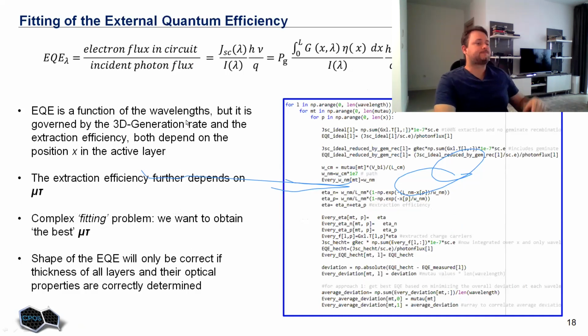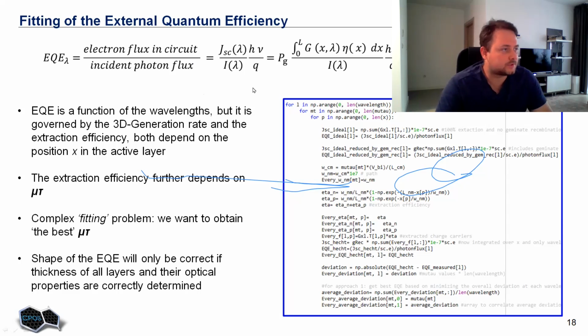So once it is done, we can proceed to the second part of what we actually added to this transfer matrix simulation script, where we can calculate the external quantum efficiency at each wavelength. For this purpose, we already know this geminate recombination prefactor. We know the extraction probability and generation rate. This is given analytically by the Hecht equation. This is numerically calculated from the transfer matrix. So we can integrate for each wavelength all over the active layer and get the external quantum efficiency.